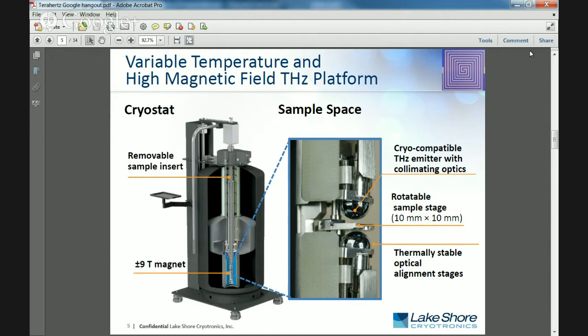Now, in order to make these emitters work in these extreme environments, we spent a lot of time putting together a cryogenically compatible package, which allows us to thermally cycle these many, many times without having to realign them or without them falling apart. Those alignment stages are both thermally stable as well as stable in these high field environments. This has taken a fair amount of work to engineer, but we found this is a really useful environment, with easy sample insertion and without having to do all the alignment, it really can move sample measurements through quickly and efficiently.